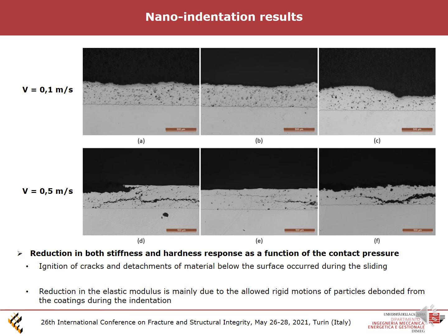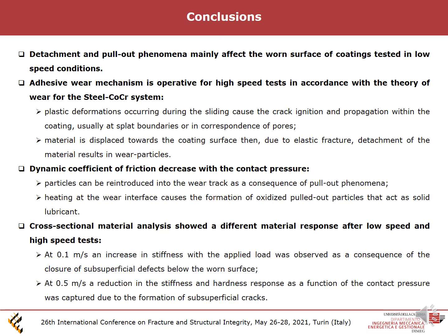So the consequent reduction in the elastic modulus is mainly due to the allowed rigid motion of particles debonded from the coatings. In conclusion, detachment and pull-out phenomena mainly affect the worn surface of the coatings tested in low-speed conditions. On the other hand, adhesive wear mechanism is operative for high-speed tests in accordance with the theory of wear for the steel cobalt-chromium system. Plastic deformations, in fact, occurring during the sliding cause the ignition and propagation of cracks within the coating, usually at splat boundaries or in correspondence of pores. So the consequent detachment of material results in wear particles.